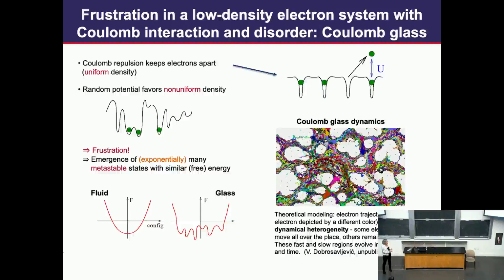This is, for example, from the simulations from Vlad Dobrosavljevic's group, where each color represents an electron trajectory. And this is a picture taken over a certain time. So you can see that there are some parts of the sample, the bright areas, where electrons basically don't move. On the experimental time scale, the dynamics is very slow. But then in some parts of the sample, they move very fast. So you can see this is heterogeneous. You have fast and slow regions, and then as a function of time, these regions also evolve. Fast ones may become slow, and so on. So this is common to all glasses.